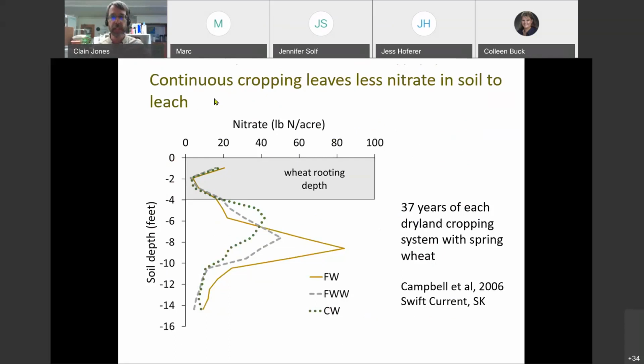Something else that leaves less nitrate in the soil to leach would be decreasing the amount of fallow. So this work is based on a 37-year study out of Saskatchewan where they monitored nitrate in pounds of nitrogen per acre and plotted that versus soil depth ranging all the way to about 15 feet deep for 3 different crop rotations. Fallow wheat in yellow, this line, fallow followed by wheat, and then another year of wheat in the dashed kind of gray line, and then continuous wheat in the green line.